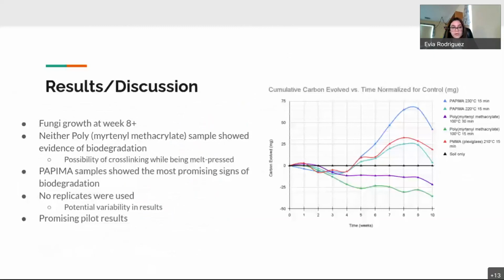Another important thing is that there's fungi growth at week 8 in my experiment. You could see it in the jars. It was filamentous. And as you can see in my data at week 8 and above, there's a decrease in the amount of carbon produced from the jars relative to the control sample. And this shows that there could be potential variability in my results resulting from the fungi growth. So if we shorten the amount of time this experiment went and remove weeks 8 and onward of my data, then you can see there's clear trends in biodegradation here.